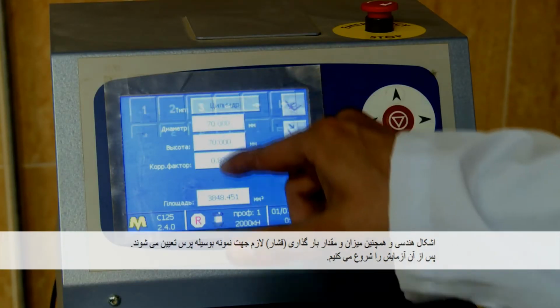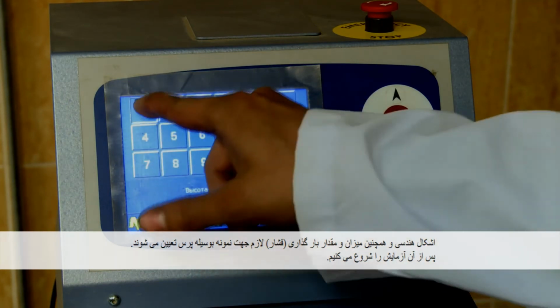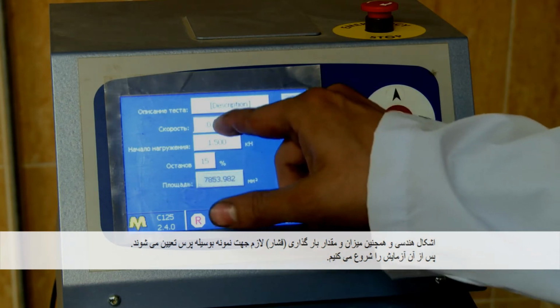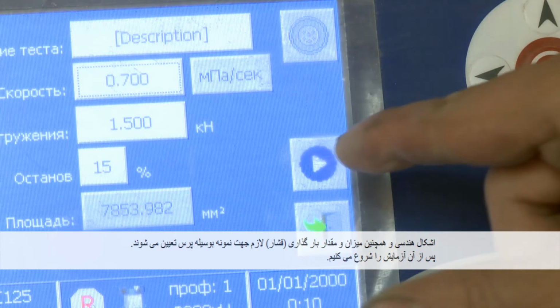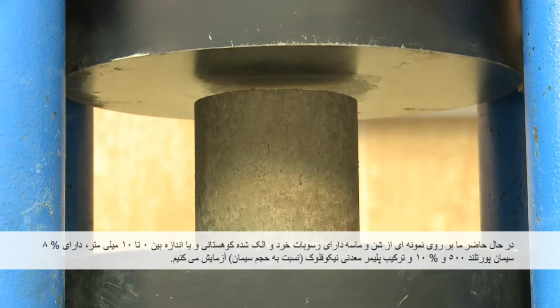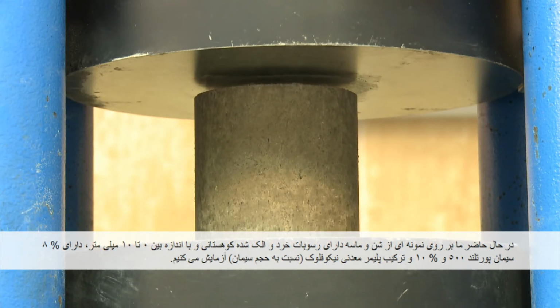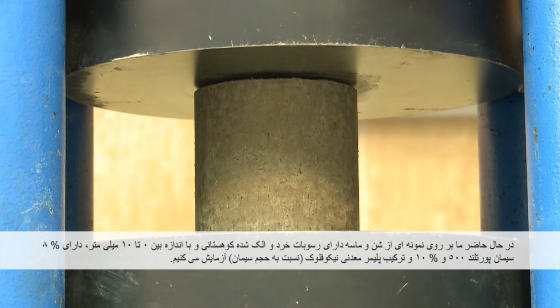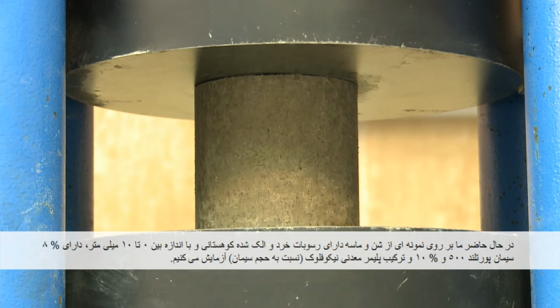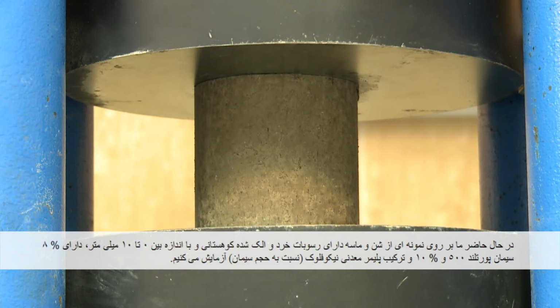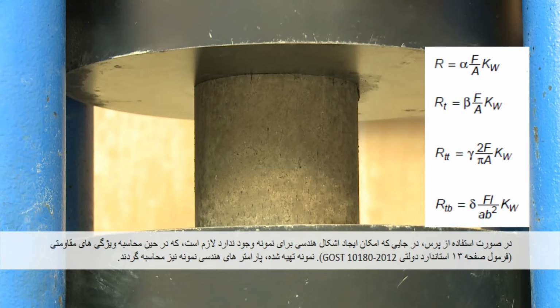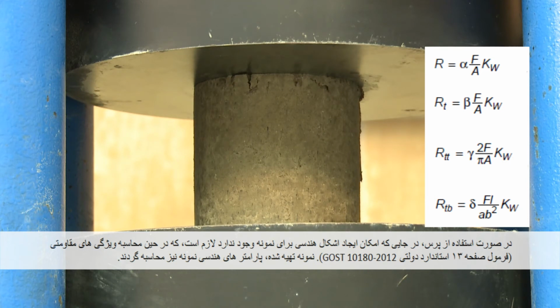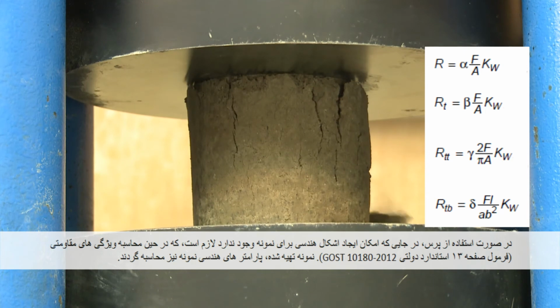Shape and dimension is set on the press as well as loading speed. After that, we can start testing. In this case, we test a sand sample with screened breakage of sedimentary rocks of fraction 0 to 10 mm, improved with 8% Portland cement of grade 500 by sand mass and 10% of MPC Nikoflok by cement mass. When using a press without specified shape and dimensions of test samples, we should take into account shape and dimensions when calculating strength characteristics of test samples. Formula on page 13, GOST 10180-2012.